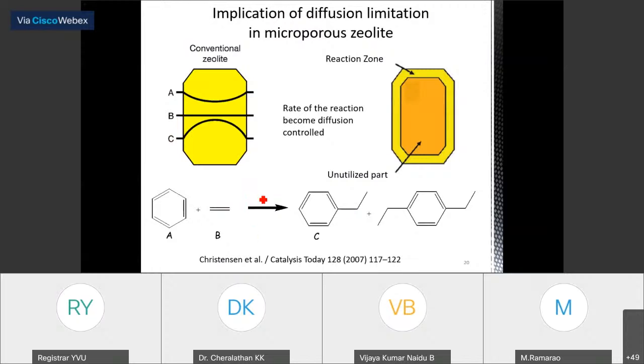Because of this kind of diffusion restriction, what will happen? Only the smaller molecules, as shown here, like this ethylene, which is a smaller molecule compared to benzene, easily diffuse into the pore, and because of that, the concentration gradient outside the crystal and inside the crystal are the same. But the product as well as the reactant, benzene, face difficulty to diffuse into the crystal due to the diffusion limitation. So what happens? Inside the crystal, the concentration of benzene is decreasing. At the same time, the product formed inside the pore is building up. The concentration of the product is building up inside the catalyst.